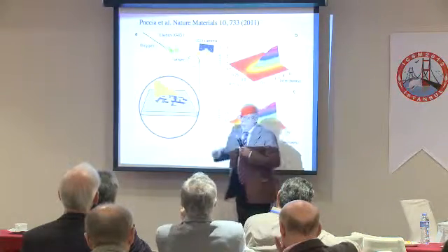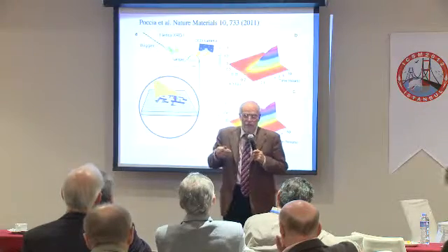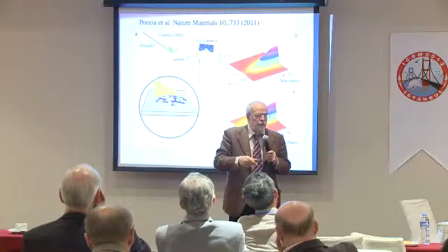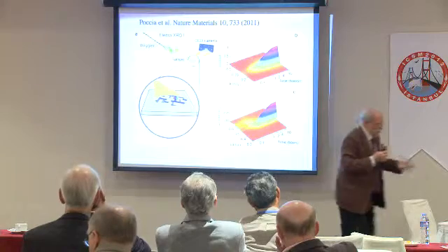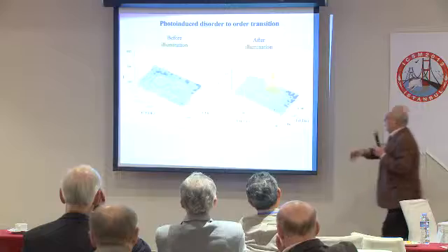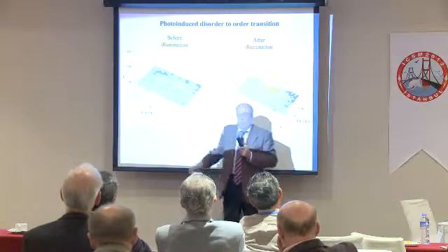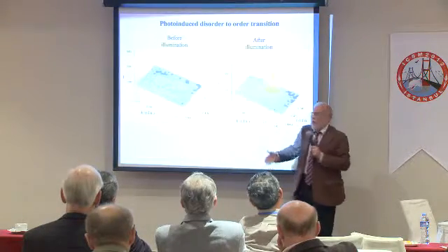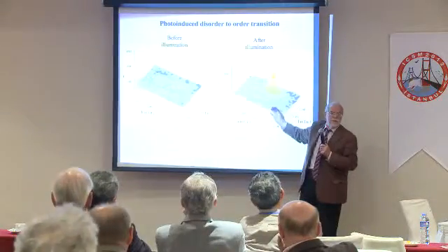What we developed is the idea of using X-rays as illumination in such a way that the penetration depth of the probe X-ray diffraction is the same as the pump. And that way we can map to the optical situation. And then we took a piece where the oxygen was completely disordered by rapid quench, and then we illuminated it, now without thermal treatment, only illumination. And then you see, after some time, this going up.